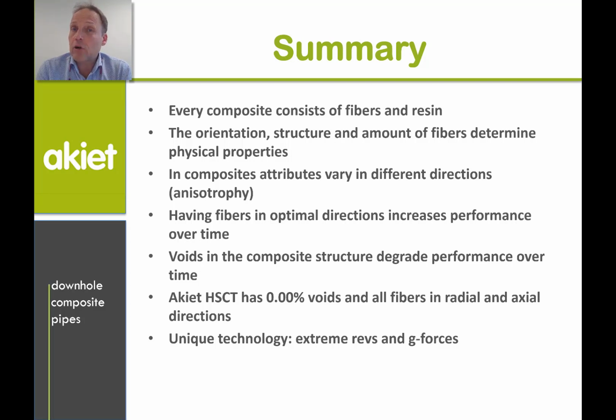Voids in the structure are always a bad thing. And there's a very distinct benefit of not having any voids in your composite structure. Akiet high-strength composite tubulars have no voids, 0.0% voids, and all the fibers run exactly in the 0 and 90 directions, which are the directions of the forces and the pressures in a downhole application. So we have a unique technology that we use, creating extreme amounts of revolutions and g-forces to result in a really strong pipe body, which is engineered specifically for downhole use, because downhole applications is all that Akiet does.